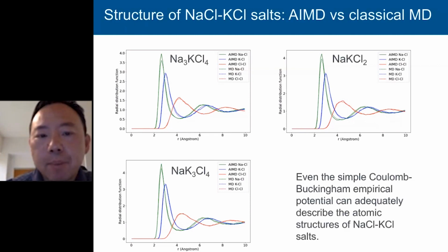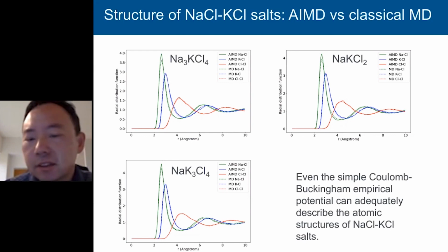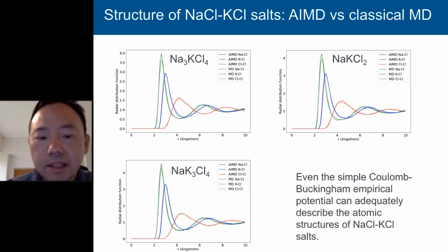So let's first compare the radial distribution functions for the sodium chloride and the potassium chloride mixtures. This figure shows the results from both Ab Initio MD and the classical MD. You can see that the agreement is excellent between the 2 computation methods over the 3 chemistries in these mixtures. So the conclusion is that even the simple Coulomb-Buckingham potential is already adequately accurate to describe the atomic structures of the salts in the sodium chloride and the potassium chloride systems. Which is very nice.